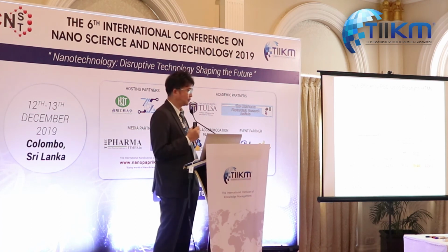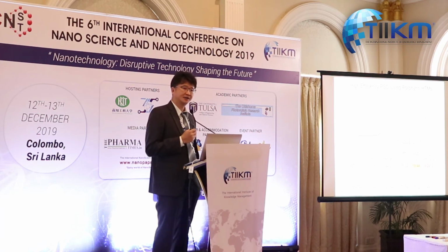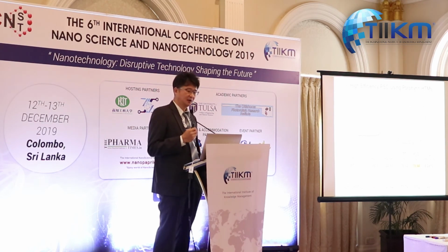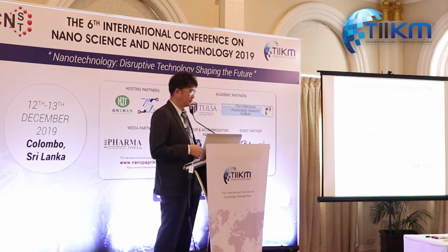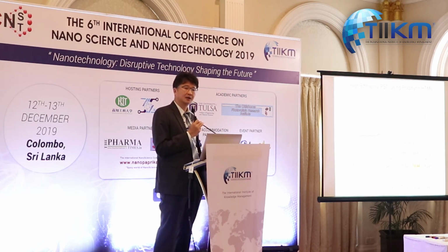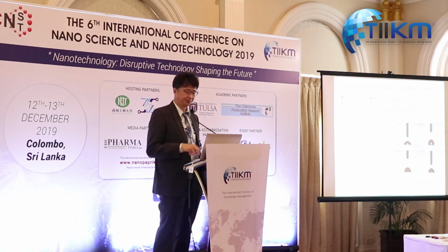All these hole transporting materials show IPCE values higher than 80% over the visible region. Among these materials, WT3 shows the best performance, giving a power conversion efficiency of 19.44%, which is better than the reference Y2 and spiro-OMeTAD.